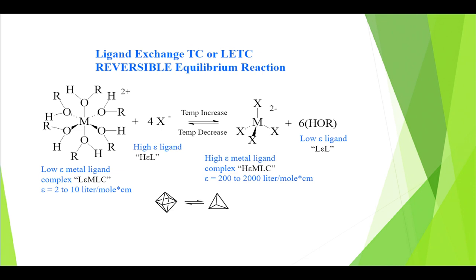As the temperature increases, if I happen to have halides around, iodine is the best one, I can change from this octahedral complex to a tetrahedral complex. And I will go from a low extinction coefficient complex to a high extinction complex. Now, notice high extinction, 200 to 2,000, is not generally considered very high. Several thousand, 10,000 is much better, 20,000 is better, but they're stuck with these 200 to 2,000, and most of them are closer to 200 than 2,000. But they can change colors.